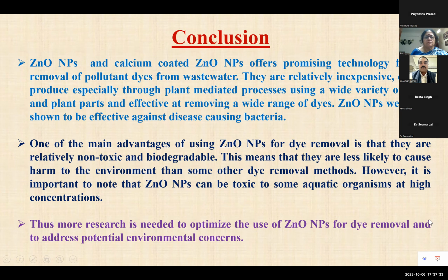Zinc oxide nanoparticles were also shown to be effective against disease-causing bacteria. One of the main advantages of using zinc oxide nanoparticles for dye removal is that they are relatively non-toxic and biodegradable. This means that they are less likely to cause harm to the environment than some other dye removal methods. However, it is important to note that zinc oxide nanoparticles can be toxic to some aquatic organisms at high concentration. Thus, more research is needed to optimize the use of zinc oxide nanoparticles for dye removal and to address potential environmental concerns.